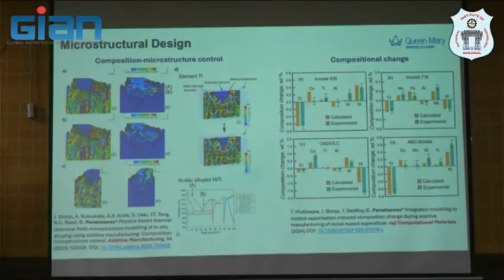So the composition and the microstructure control here has been very important in the rapid heating solidification process, like I said before, because in this binary system, nickel titanium, you will see that it's not homogeneous. It's actually heterogeneous solidification. You will see some distribution of the nickel and titanium separately, and that means there will be some grain which is formed inside the Melpool before surrounding with liquid, so equiaxed may form something like that. So this provides an understanding from the nickel titanium system based on a simple binary system. So it inspires us to look at this in nickel-based superalloy, which is a multi-component system.